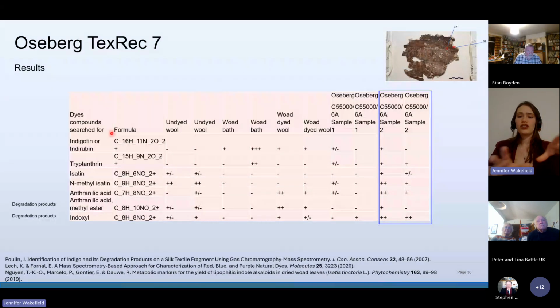So we then search specifically for the dye compounds that you find in woad. And this indigotine is what's present in woad. It's also what's present in the indigo dye that's from India, but woad is one that's more generally accessible in Europe. And what we found is we didn't find that mass present on the undyed wool, which reassures us that when we do find it, it is because it's from the woad.